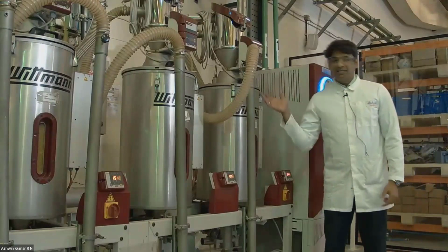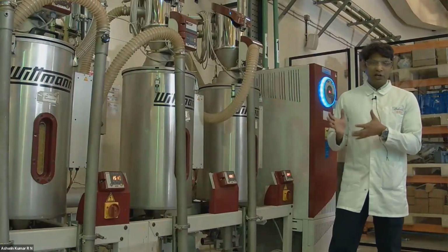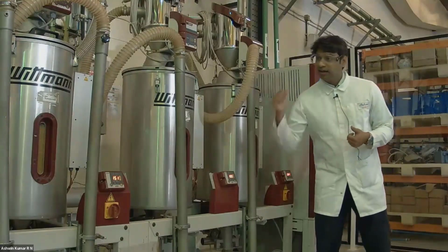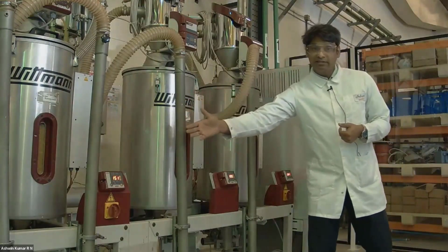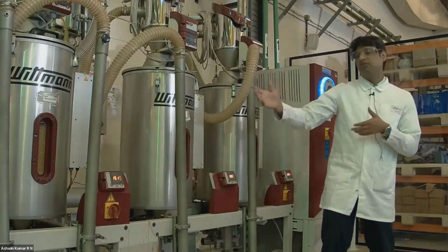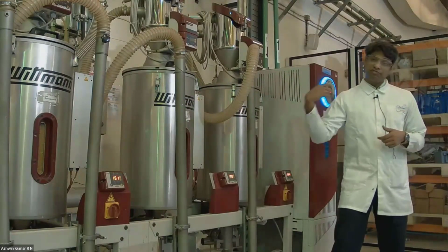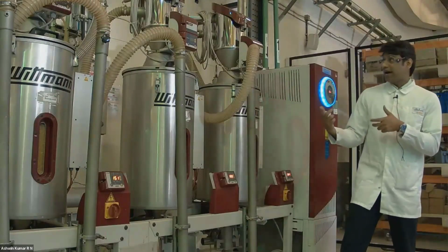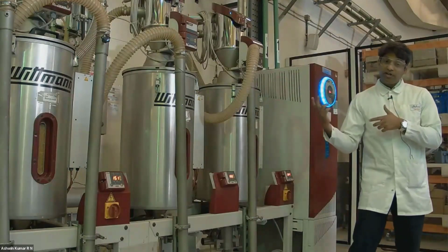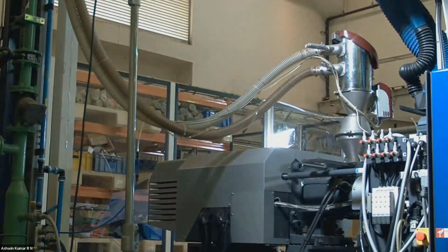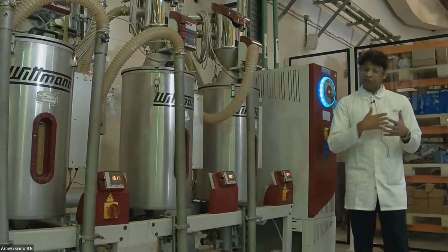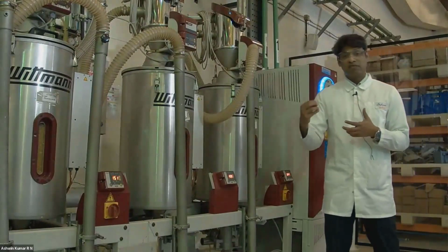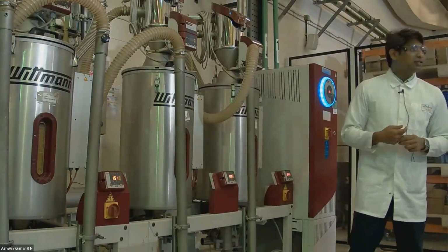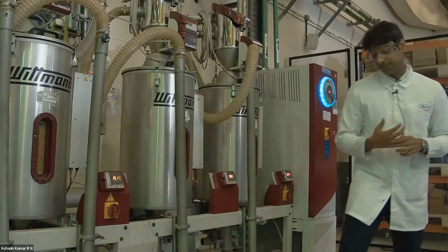Now, this is the dryer system we have. It's a completely closed-loop dehumidifier kind of dryer. We have been pre-drying Ultem at 150 degrees C for about 4 hours. As you can see, it has about 50 liters of capacity. And I want to highlight a feature here. From the dryer to the machine hopper, it's a completely closed-loop system wherein the material is automatically conveyed into the hopper, to have a streamlined, non-stop auto cycle molding process. Now, let's quickly go back to the other setup which we have here.